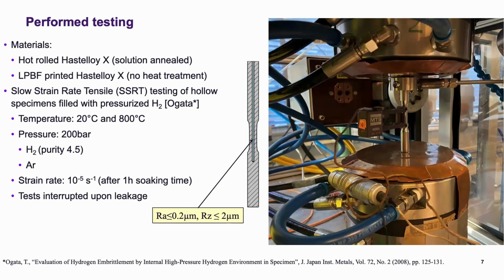And I show here that also the internal surface roughness is kept to within the limits of, or what is expected to be the limits of, this standard that is under development. And here we don't see this, we only see the room temperature tested up, but the heating would be achieved by an induction coil around the specimen.